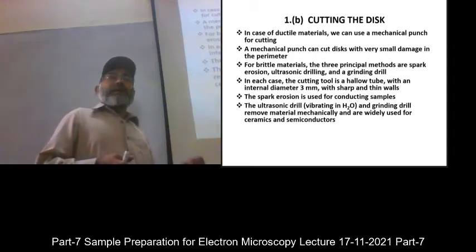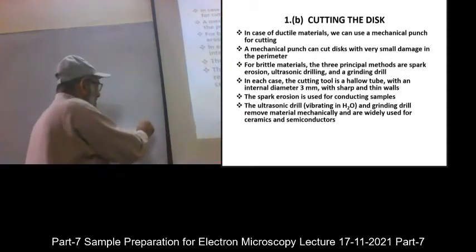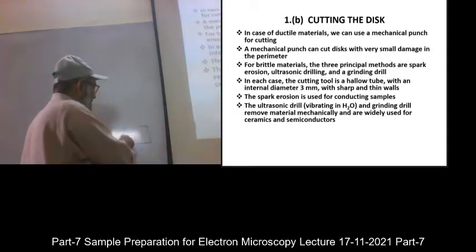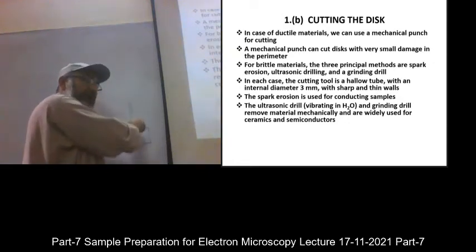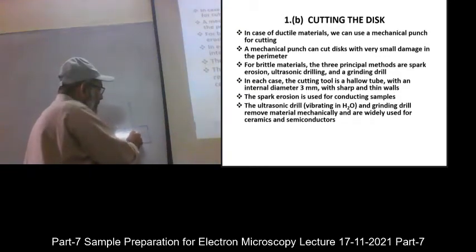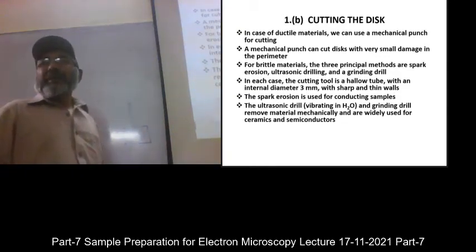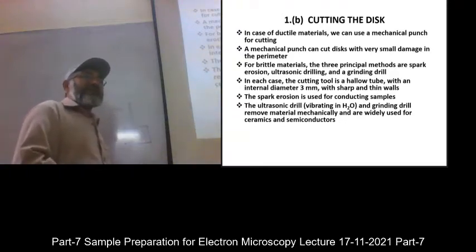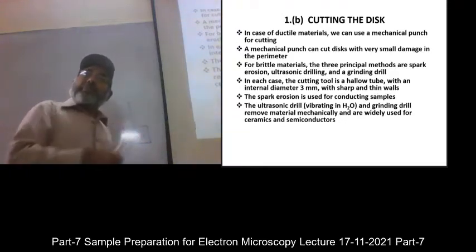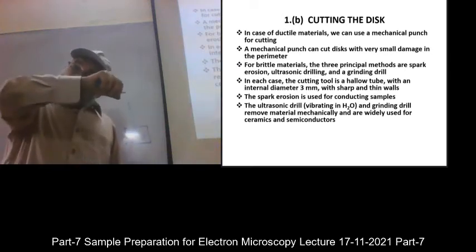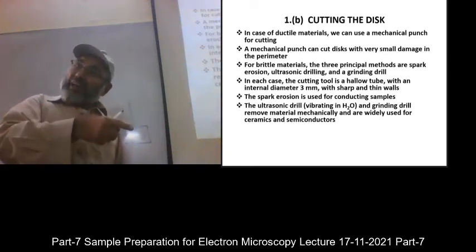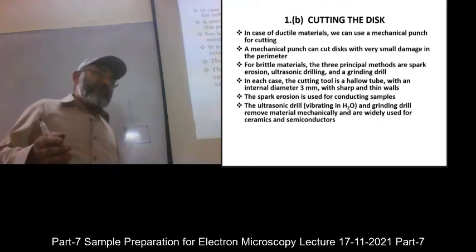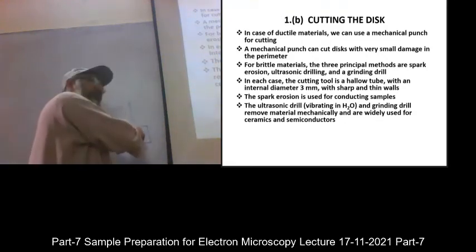The silicon carbide powder may be a kilo for a few hundred or for a couple of thousand rupees. And where that silicon carbide powder is used, you put the sample here on a very hard glass like this, and ultrasonic drill is coming like this. It is like this hollow tube. And when you start it, you put silicon carbide powder here and a little bit water. So the pipe pressurizes those powder. The powders are very hard, just like diamond, right? And it is very fine.